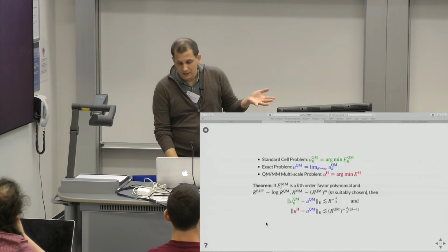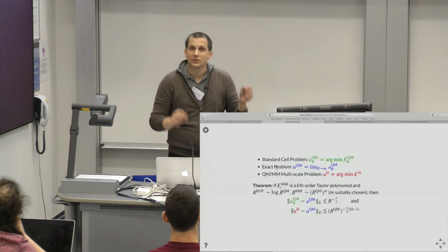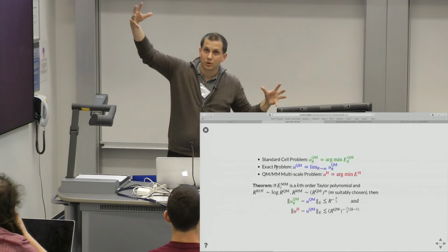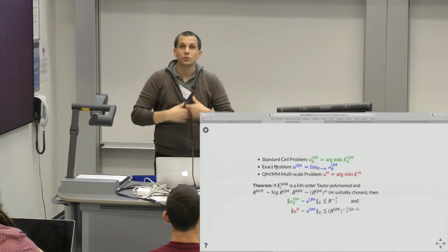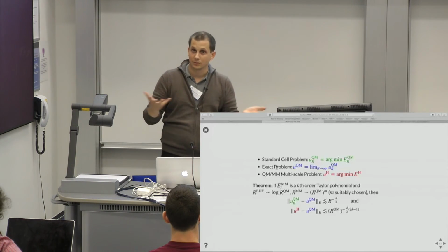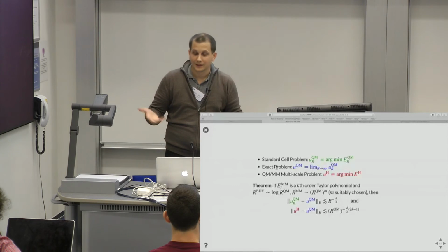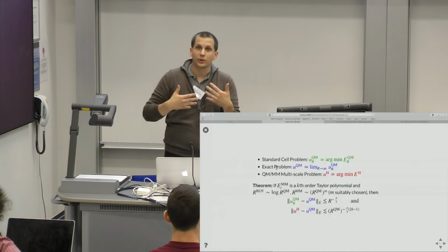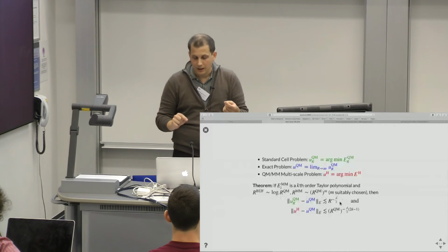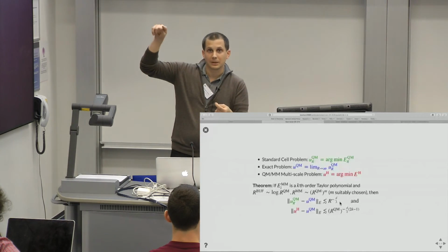So what you actually do is define the infinite problem as a limit of finite cell size problems. That's true for all of these: the crack problem, the interstitial problem that I showed you. For a little point defect, the rate is diameter to the minus dimension over 2.